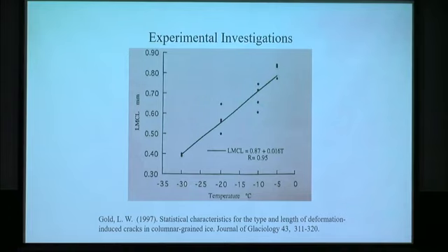Finally, the dependence of this crack length on temperature, again from -35 to close to 0. You can see that the colder it is, the shorter the cracks. So this is what was experimentally observed.